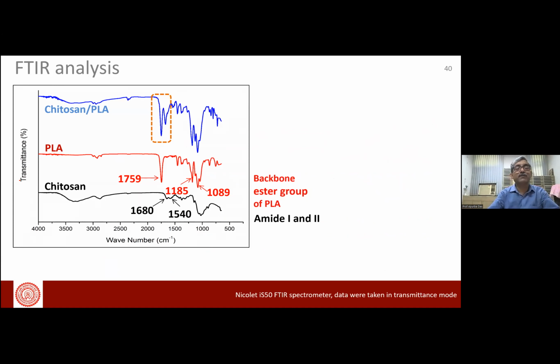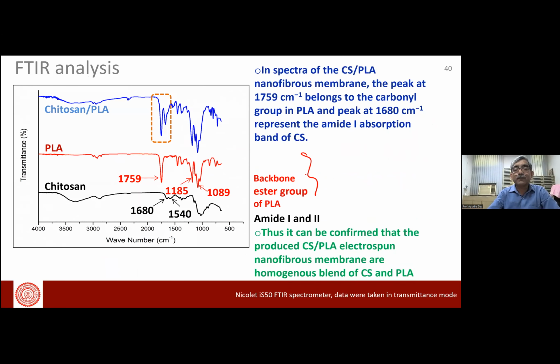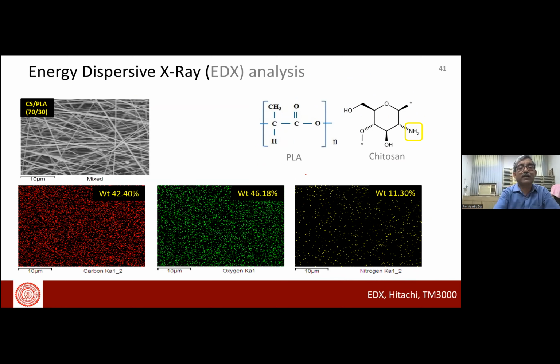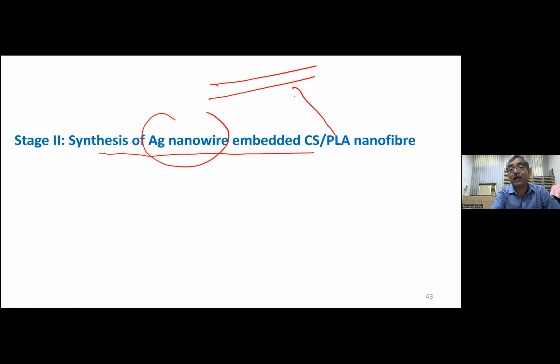Okay, and this FTIR is showing that it's a combination of PLA and chitosan. Now, after that, here these are the different proportions of oxygen, carbon, and nitrogen, which show that it's a proper blend of chitosan and PLA. Now we have tried to synthesize silver nanowire on this nanofiber. Inside the chitosan PLA nanofiber, we have developed the silver nanowire, so as to improve the antibacterial activity further.